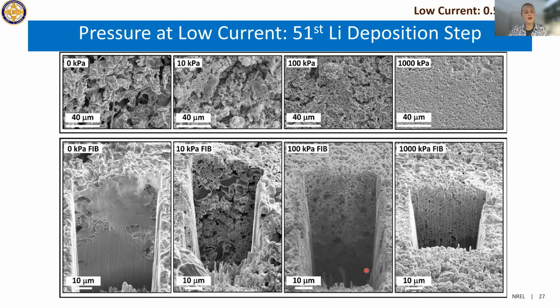Okay, so at low pressure, we really wanted to understand what happens after that first cycle. All the images you were seeing before were the first deposit of lithium. Now this is after 50 cycles of plating and stripping, so this is the 51st plating step on the working electrode. What you're seeing here for the low current conditions is that there's a lot of electrolyte filling in the low pressure electrode. Due to all of the porosity, we weren't able to dry out that electrode enough to get nice clean images. A lot of this is electrolyte that was heating up under the electron beam as we were imaging it.